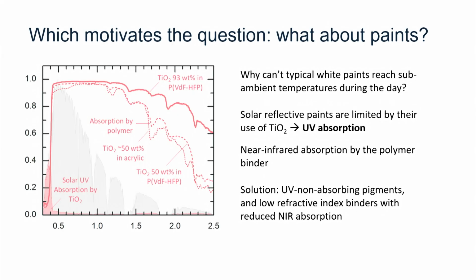Why can't it achieve this kind of radiative cooling effect? It turns out the fundamental problem is really around this UV problem and UV absorption. So the primary pigment that is used for white paints is a material known as titanium dioxide. Pretty straightforward to use. It's been used for a very long time, but it's extremely absorbing of the ultraviolet.